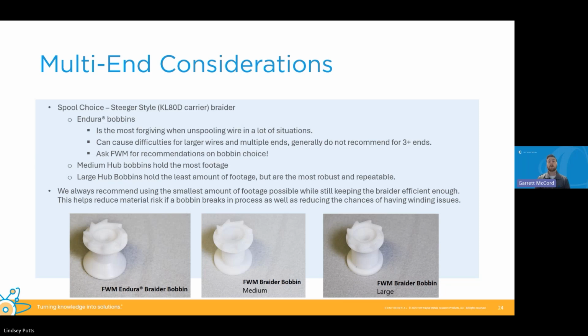The medium hub bobbin can hold the most footage for the most uptime on your braiders. However, the trade-off is that the spool is not as sound with the strength. And then the large hub bobbin can hold the least amount of footage, but they're the most robust and repeatable when it comes to spool integrity. And we're always recommending that we use the smallest amount of footage possible while we're still keeping the braider efficient enough. This helps reduce the material risk if the bobbin does break, and also helps us to reduce the amount of spooling issues.